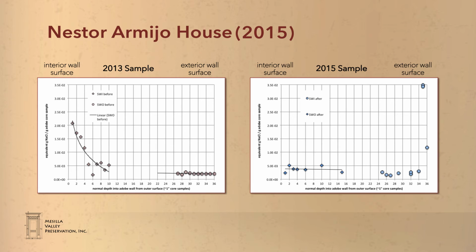In other words, we have succeeded in reversing the abnormal flow of moisture and salts in this very salt-affected wall. The natural behavior of this wall has been reestablished. The highest concentration of salts are being promoted to the exterior surface, into the lime plaster layer, which is just exactly what we had hoped to see happen. At the time of this testing, no salt damage was yet visible in the exterior lime plaster layer.